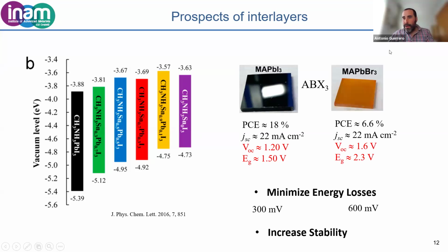Okay, we also make quite well the formulation with the bromide, and in this case we get open circuit potentials of 1.6 volts, which are amongst the highest open circuit potentials of this type of formulation. And this is because we are getting very high quality films, and we can minimize energy losses with this type of materials.